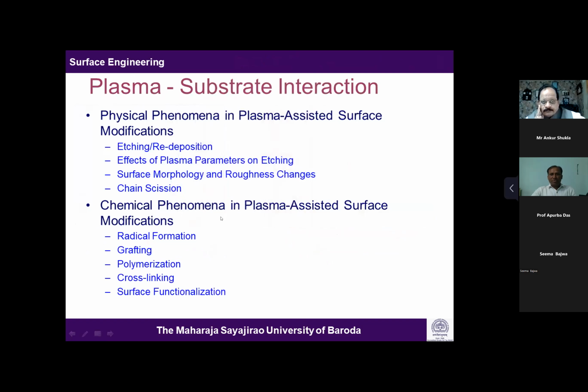I would like to say a few things about the mechanism, that is, the surface plasma substrate interactions. It can be understood in terms of physical phenomena, like etching. One physical change that takes place is surface etching of the material, because of the plasma species and also the UV radiation. We require this for most applications, particularly technical textiles. One successful application is interfacial bonding strength improvement, particularly for composites. This is required because if you have a smooth fiber, then the bonding at the interface will not be good. So we require some surface roughness, where this technique is much used.